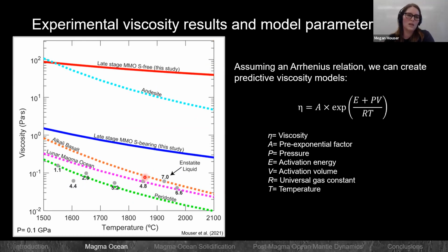So when we go back to the experimental data, one thing that we can do is create a predictive viscosity model. We can do that by assuming an Arrhenius relation shown here. We have each of our respective data sets with our pressure, temperature, and viscosity data, and we can run a nonlinear regression through each data set and extrapolate a parameterized value for A, the pre-exponential factor, E, the activation energy, and V, the activation volume. Once we have these three parameterized values, we can plug in whatever pressure-temperature condition we want, and we can get a predictive viscosity.